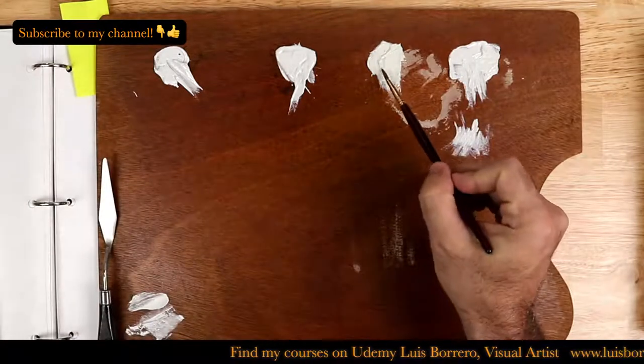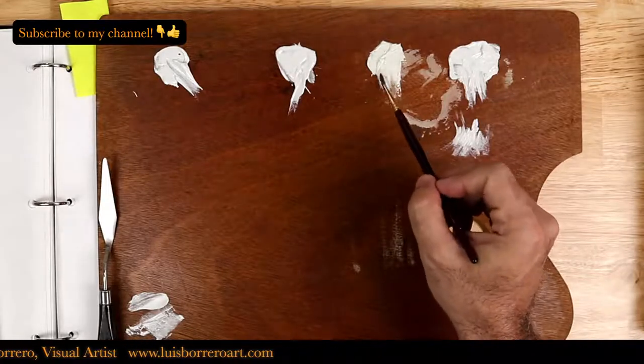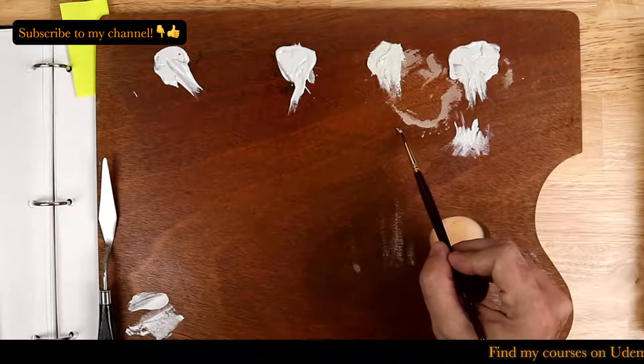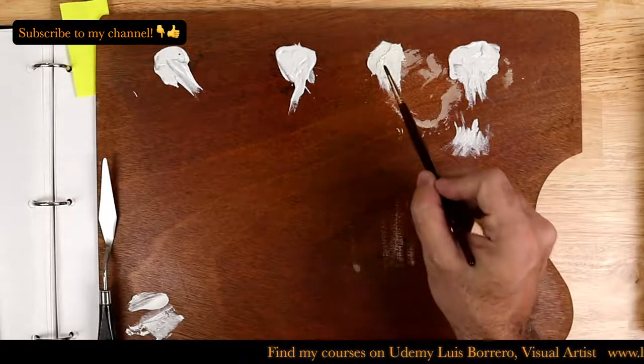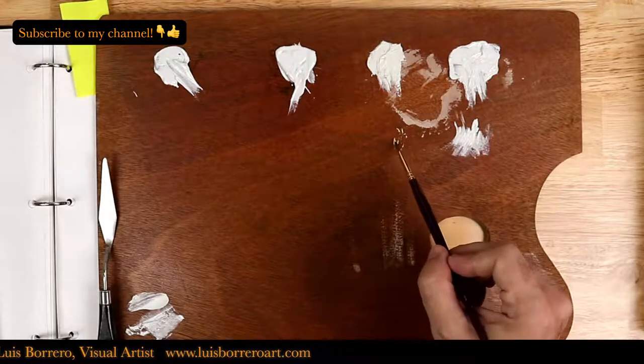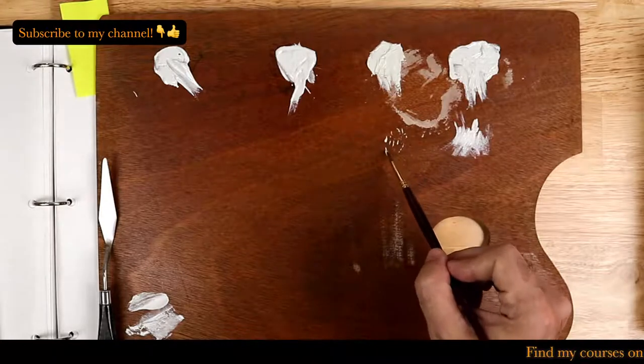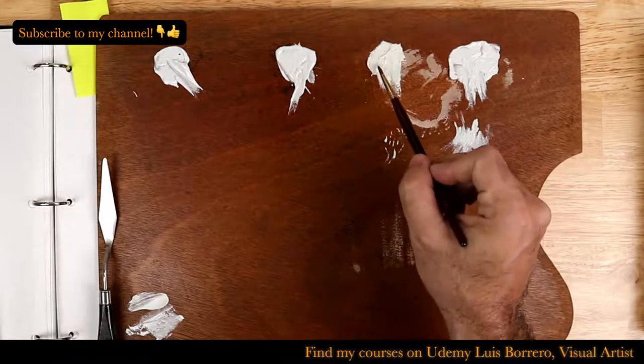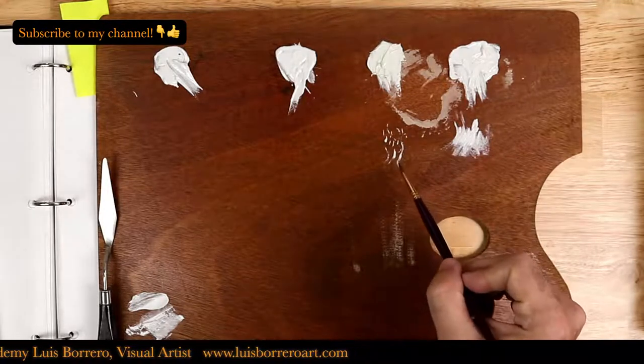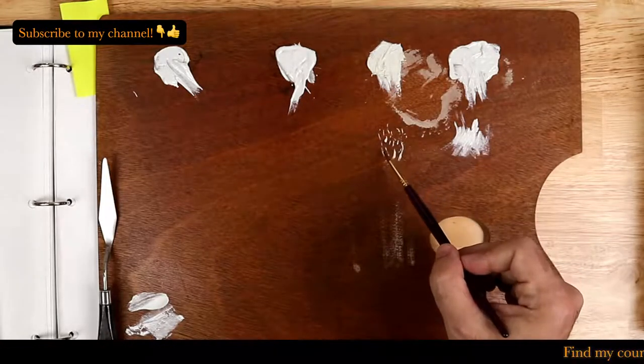The second sample, let me clean my brush here. The second sample is heat-bodied oil. Within the heat-bodied oil range, there's also a lot of variation, because it depends on how long the oil was heat-bodied. There you begin to see some different effects. The paint is long, meaning it has this stringy quality, but it's still very dry. You see this effect in a lot of oil paintings from the past, this string quality.